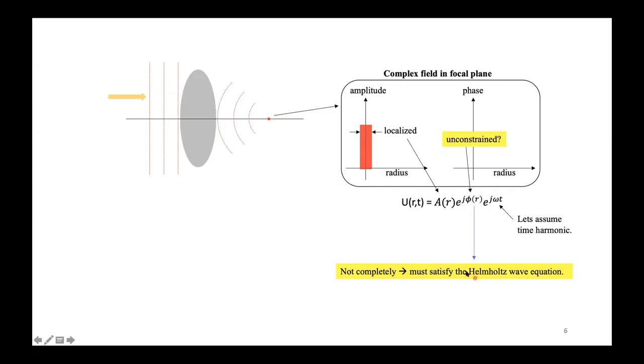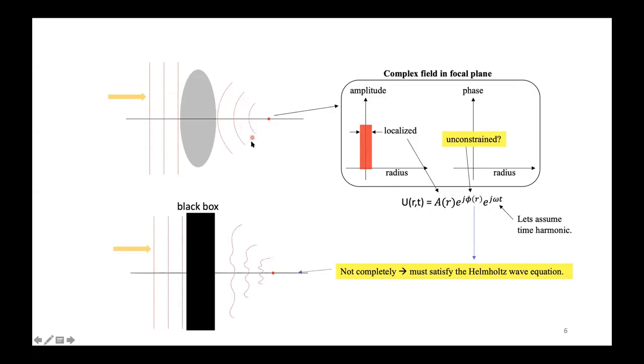However, conceptually, this tells us that if I put a localized field with an unconstrained phase, with some constraints, let's say, but minimal, weakly constrained by the Helmholtz wave equation, and apply back propagation, then I am not necessarily limited to these nice converging spherical waves or even the conjugate of the electric dipole, as theory shows. It turns out there are many other waves that can actually induce the focusing. So another way to think about what I'm trying to say here is that phase in the focal plane is a free design parameter that allows us to essentially pick the phase in the black box here that can turn the plane waves into some superposition of waves, which will end up with a focused amplitude or focused intensity.